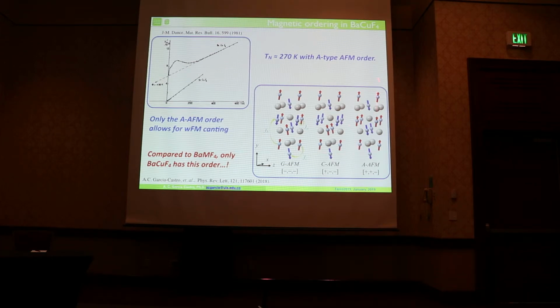Interestingly, this is the only ordering that allows the weak ferromagnetic contribution, the weak ferromagnetic moment, and it is the one that has been observed experimentally. When we check the calculations, we observe clearly that this is the ground state of the system.